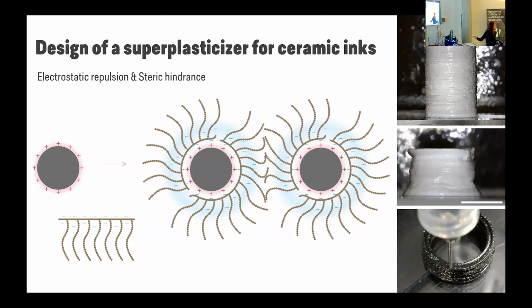So if you really don't optimize, you cannot have these towers of filaments that you could do. And then we optimize these systems by really working on the steric hindrance. We modified the side chains of a polymer, the density of the side chains and the length of the side chains, in order to really reach the theoretical limits of these loadings. But inks are different, they flow. And in here, I am talking about the dose.